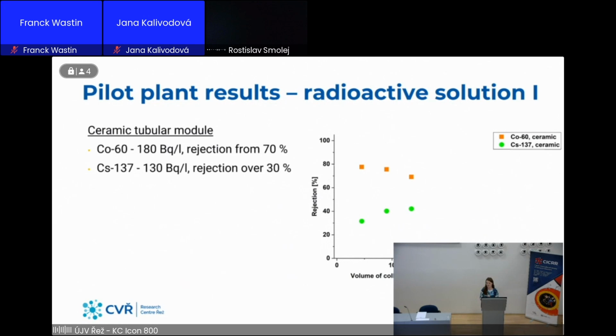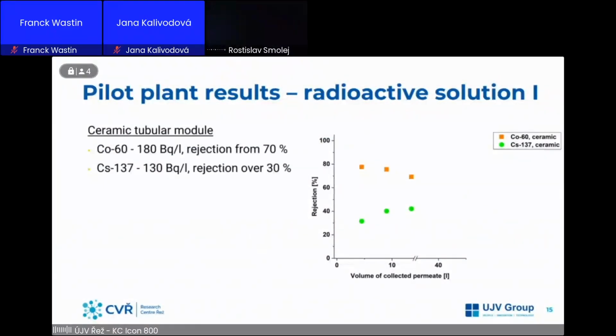As I said at the beginning, we also tested this setup with the liquid radioactive solution. We had two types of solution. One was from the nuclear power plant, and the other one was from the experimental reactor. The ceramic membrane behavior was very similar to what we've seen with the non-radioactive model solution, both with rejection of the cobalt-60 and the cesium-137. On the slide, you can see the starting activities of both radionuclides in the inflow feed.